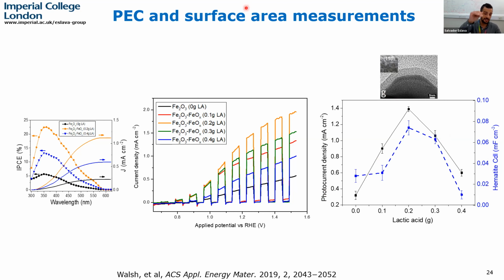So achieving these 10 nanometers of amorphous layer, the final films have higher photoelectrochemically active surface area. And this explains the best photocurrents we achieved. And this was remarkable because we achieved 1.5 milliamps per square centimeter with a single step, because in one step we form both the semiconductor and the electrocatalyst.